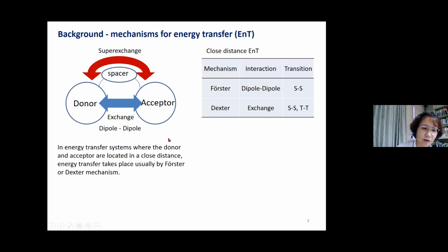So please let me remind you about the mechanism for energy transfer in normal cases. If the energy transfer occurs at a close distance, as you know, two famous mechanisms are known. One is Förster and the other is the Dexter mechanism. In the case of the Förster mechanism, the main interaction is the dipole-dipole interaction, and this causes singlet-singlet energy transfer. On the other hand, in the Dexter mechanism, exchange interaction governs the energy transfer rate, and in this case, singlet-singlet and triplet-triplet energy transfer can both occur.